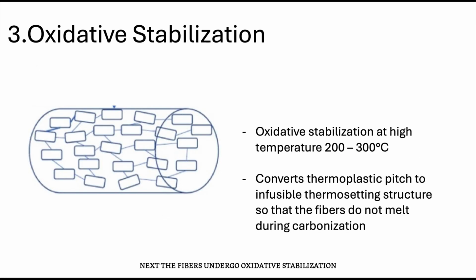Next, the fibers undergo oxidative stabilization at around 200 to 300 degrees Celsius. This step converts the thermoplastic pitch into an infusible thermal setting structure so that the fibers do not melt during carbonization. If stabilization is insufficient, the fibers may melt during carbonization, while excessive stabilization can degrade mechanical properties.